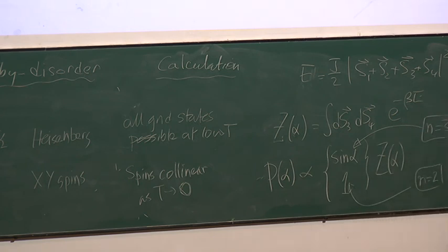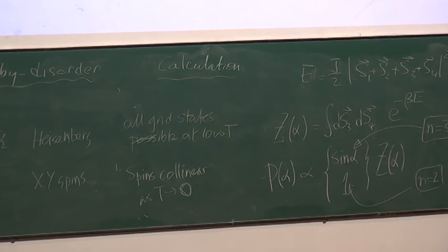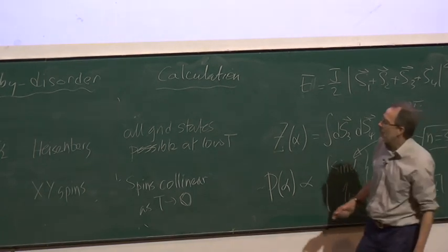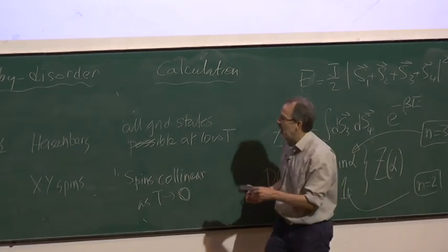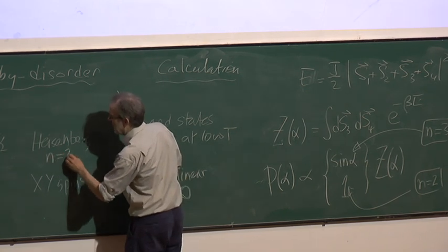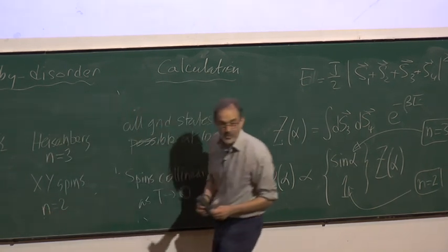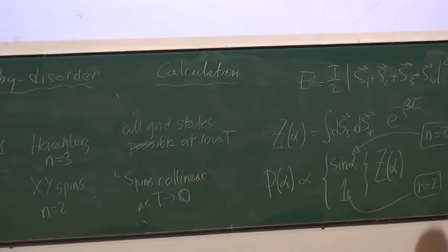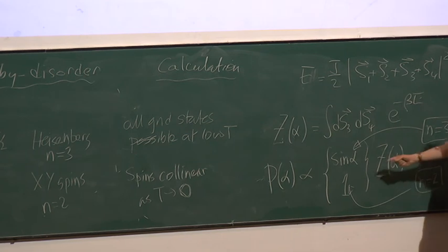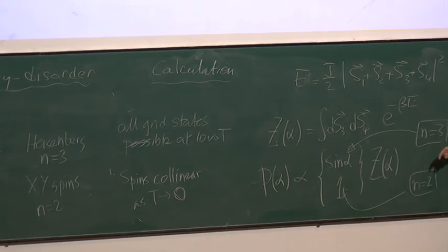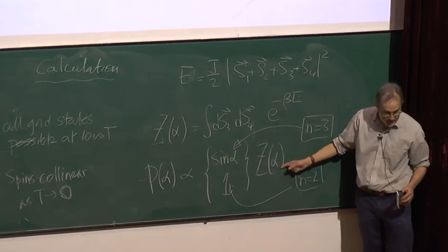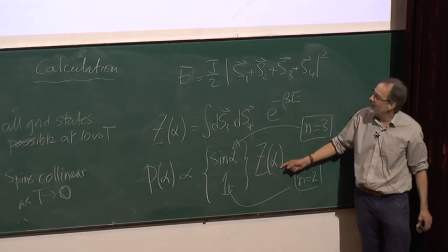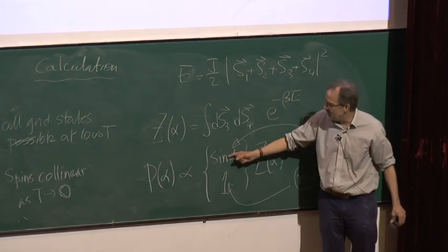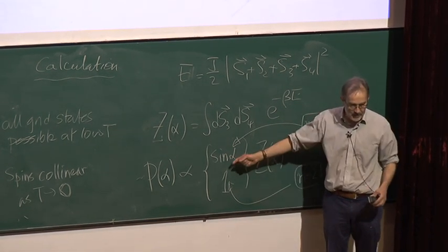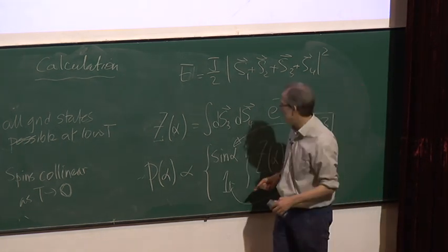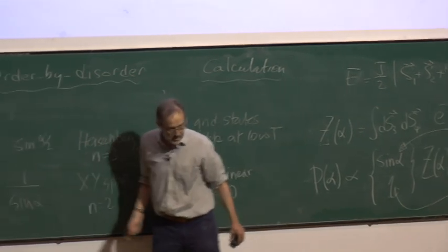So this is the same as this. So here, we said Heisenberg spins have sine alpha. Heisenberg is n equals 3, and here n equals 2. So here we do have to get sine alpha, and then it's sine alpha. There are two factors: there's the partition function from integrating out 2 of the spins, and then there's the volume factor from the relative angle of the remaining 2 spins. When I combine them both, then I get this probability distribution.